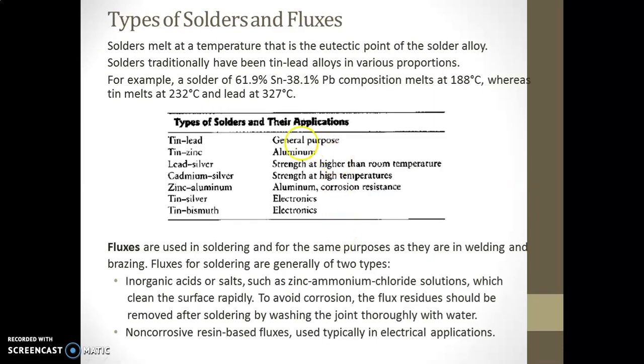So, types of solders and fluxes. The solder metal melts at a temperature that is at the eutectic point of the solder alloy, and I'll give one example of solder in which tin is almost 62% and lead 38% composition, which melts at 188 degrees Celsius, whereas tin melts at 232 degrees Celsius and lead at 327 degrees Celsius. These are some of the types of solders along with the applications.